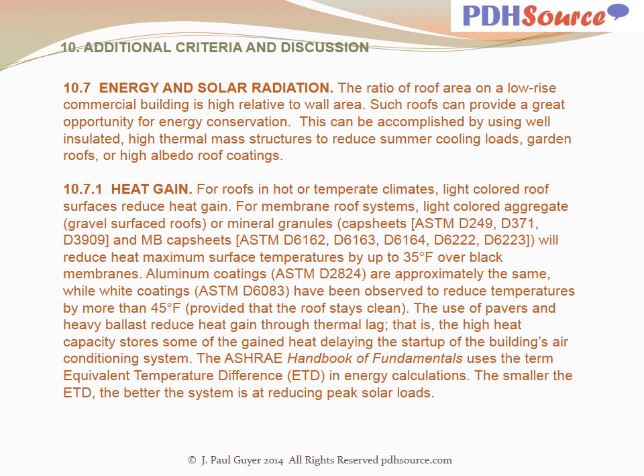For membrane roof systems, light-colored aggregate, gravel-surfaced roofs, or mineral granules and MB cap sheets reduce maximum surface temperatures by up to 35 degrees Fahrenheit over black membranes. Aluminum coatings are approximately the same, while white coatings have been observed to reduce temperatures by more than 45 degrees, provided that the roof stays clean.